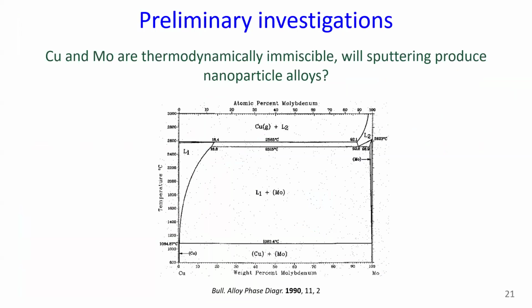So as our preliminary experimentation, I want to offer an example of some of the things that we can study. And the first question that we asked as a proof of concept for our system is whether we can sputter a copper molybdenum alloy. Conventionally, copper and molybdenum phase segregate because copper is an FCC metal and molybdenum is a BCC. And so through colloidal chemistry, it's virtually impossible to create an alloy using copper and molybdenum. And so we were interested in how this gas phase synthesis would affect that.